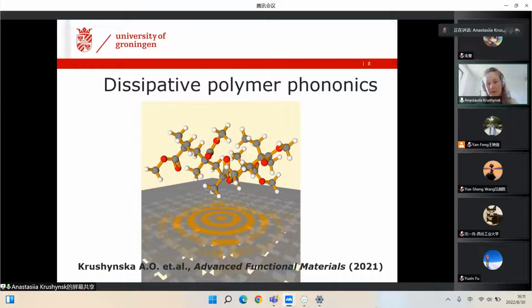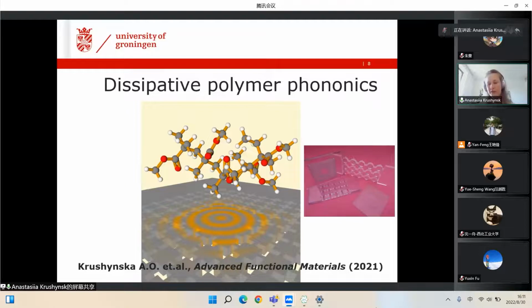And how the secondary relaxation zones, being very small and resulting in small variations of elastic moduli, can influence the dynamics of phononic structures. So for that, we prepared some samples of phononic plates with band gaps at different frequency ranges, and showed that secondary material relaxation in polymers can introduce large changes in the wave attenuation of phononic plates, depending on the relation between the material properties and the frequency band gaps, and also the mechanism of these band gaps.